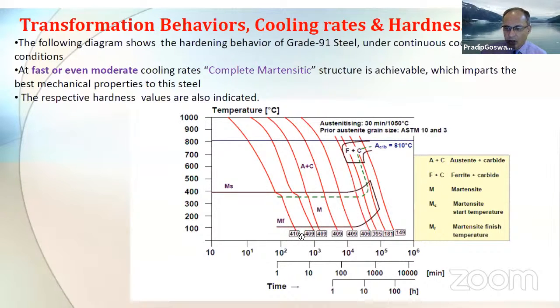it's a mixture of ferrite plus carbide, which makes the steel quite soft. So you see here that a very well-cooled martensitic structure before tempering can have a hardness of 390 to 400, typically in Brinell. But when it is cooled very slowly, you can have a hardness level as low as 180 to 150, which is definitely not the right grade of P91 material. But having said that, if this alloy is properly cooled, if it is thoroughly taken care of, it could give a hardness in as-cooled condition of close to 400 Brinell, or an equivalent number in Vickers.